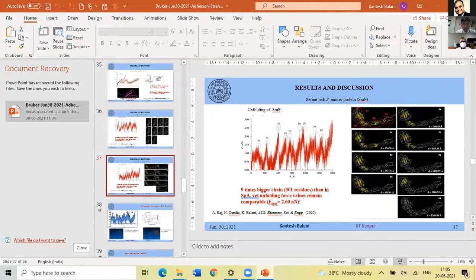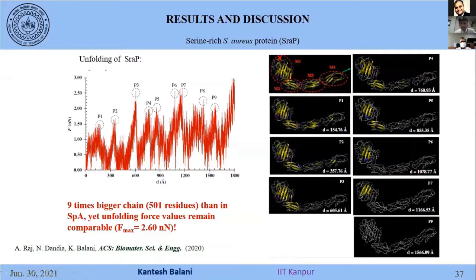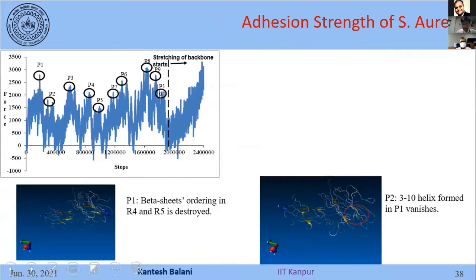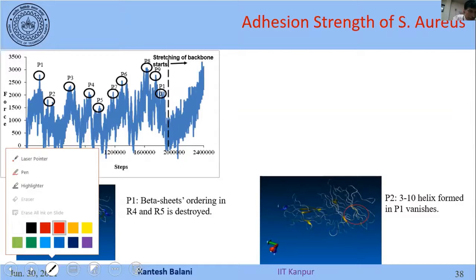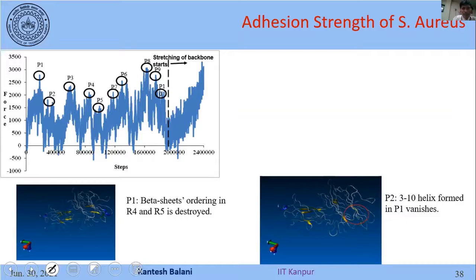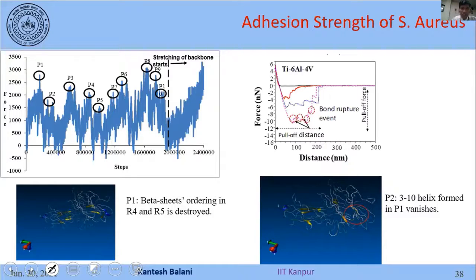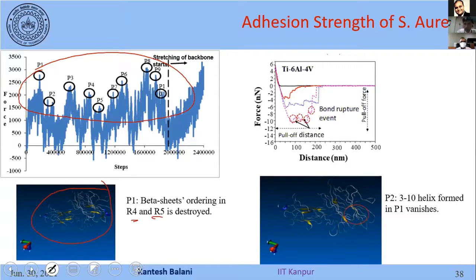And now even if we go for this 10 times bigger chain, we are still seeing the forces are in the region of around 2.5 to 3. Okay, that's okay. I just mentioned that it takes time, so we are going back and translating, and now we're able to link that our forces are of the order of 2.5 to 3 nanonewtons. Then what is happening at each and every location? We can now see there were some alpha helices, some regions R4 and R5 which are now disappearing, or some beta sheet or alpha helices are getting destroyed. So that part you can basically see at each force what might be happening.